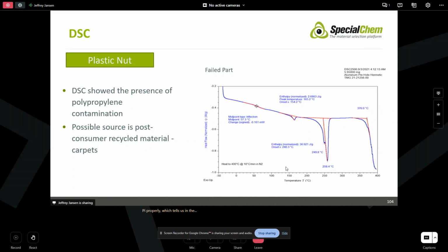That polypropylene is going to be a little softer material, probably not going to be very miscible with the nylon. So it's probably going to lack the glass and mineral filler. It'll be softer, going to allow that nut to strip out. And so that again is what we're identifying there.